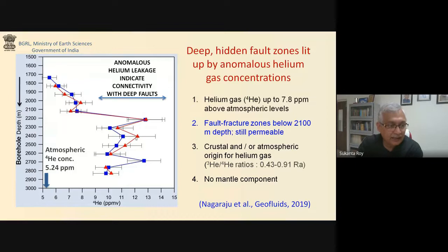As you can see, on the left panel, below a depth of 2100 meters, the helium levels reach very anomalous levels, much higher compared to the atmospheric concentration of 5.24 parts per million. We even measured up to 7.8 parts per million above the atmospheric levels. And these were certainly indicative of fault fracture zones below 2100 meters, which are still permeable.